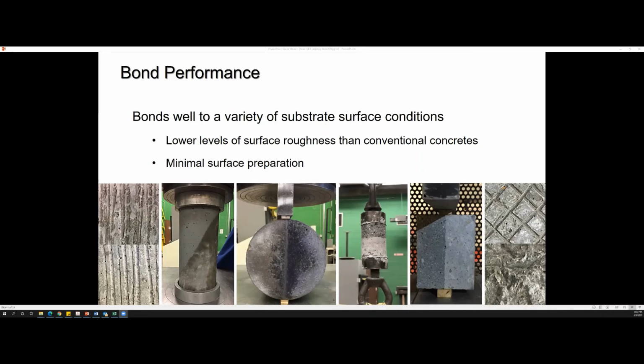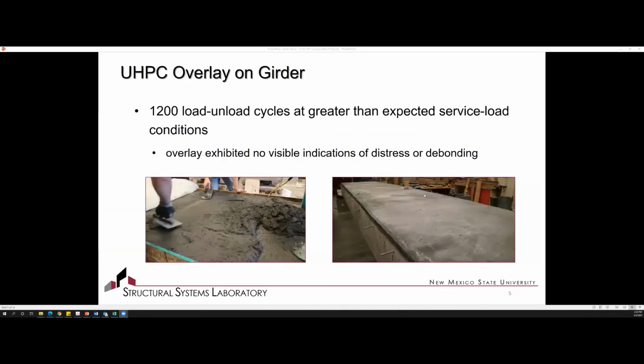After some tests, we then put this UHPC on a girder that we had in the laboratory. We actually put a 1-inch overlay on this girder you can see here. Then we subjected this girder to 1,200 load unload cycles at greater than expected service load conditions, meaning that we displaced it much more than what we'd expect to see under truck loading. After those 1,200 load unload cycles, the overlay exhibited no visible indications of distress or any debonding issues on the girder. We then took the girder to failure.